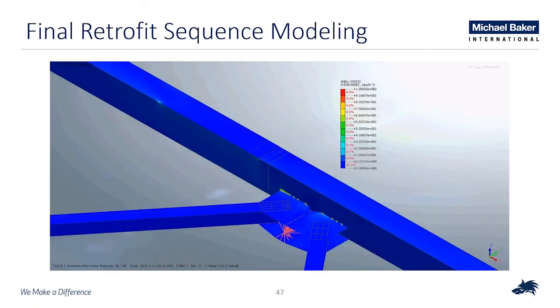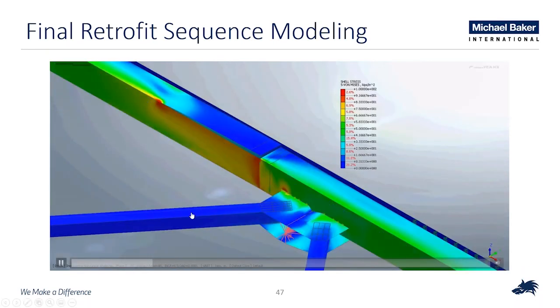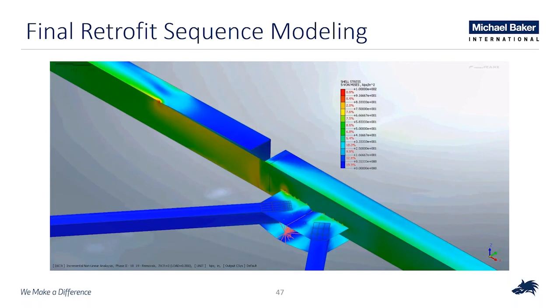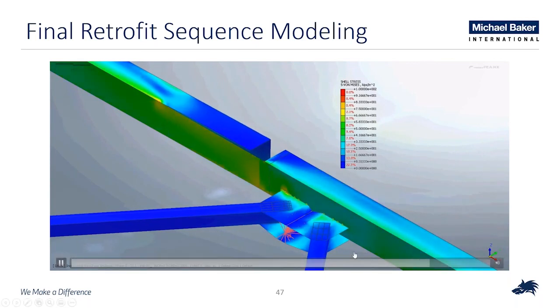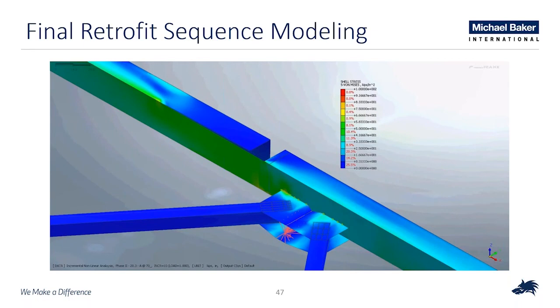So here there is a little video of the retrofit sequence modeling. You can see the application of dead load, the removal of one of the inboard plates. Then as we are applying a little bit of the PT forces, the unloading takes place. So gradually unloading. Then eventually you will see the outer plate starts to buckle out because of the compressive forces. Then it's removed along with the removal of the fracture location. And the final stage, the final PT forces are applied, which is basically you can model the entire repair procedure for the local model fairly accurately. And in terms of the local behavior, it matched up pretty well with what was observed in the field.